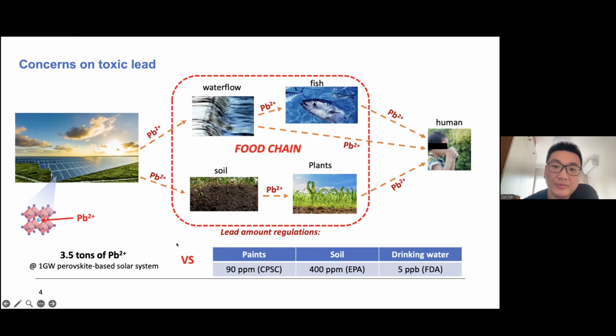This is a very typical example of the numbers. A 1 gigawatt perovskite-based solar system contains around 3.5 tons of lead. If you compare to paints or soil, the lead concentration is strictly limited. For paints used in our daily life, the lead concentration should be below 90 ppm, that's parts per million. For drinking water, it's 5 parts per billion. So lead ions are strictly limited in daily life, but if we have a perovskite-based solar system with so much lead, it's a big concern.